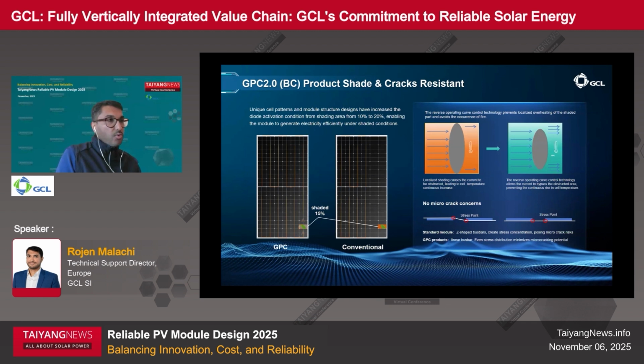Here again, just to focus on the reliability features of GPC 2.0, here specifically the shading. Conventional modules trigger the bypass diodes once roughly 10% of the cell string is shaded, which results in lost power and local heating. With our GPC design, optimized cell patterning and circuit layout increases the activation threshold to around 20%. This means the module continues generating energy even under partial shading conditions, delivering high real-world energy yield.